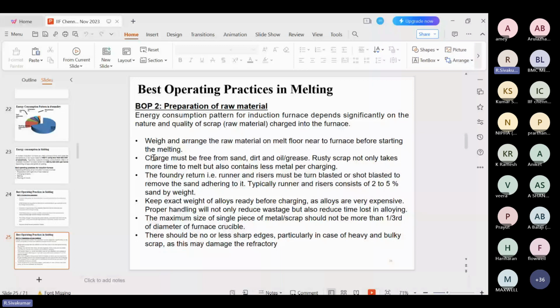And the charge must be free from sand, dirt, oil and grease. Rusty scrap leads to more slag formation and contains less metal per charge. So it leads to more slag formation inside the crucible. If slag is increasing, the power consumption also increases. It also reduces the metal output.